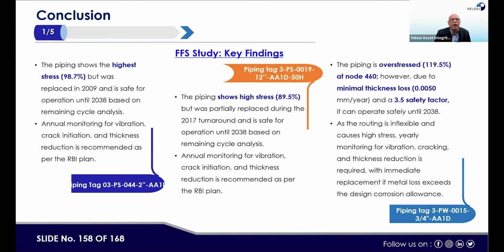So conclusion and recommendation is the last part. The piping shows the highest stress, 98.7%, but was replaced in year 2009 and is safe for operation till 2038 based on the remaining cycle analysis. Annual monitoring for vibration, crack initiation and thickness reduction is recommended as per the RBI plan. Then the piping shows high stress, the other one, this is tag number 0019, 89.5%, but was partially replaced during the year 2017 turnaround and is safe for operation until 2038.